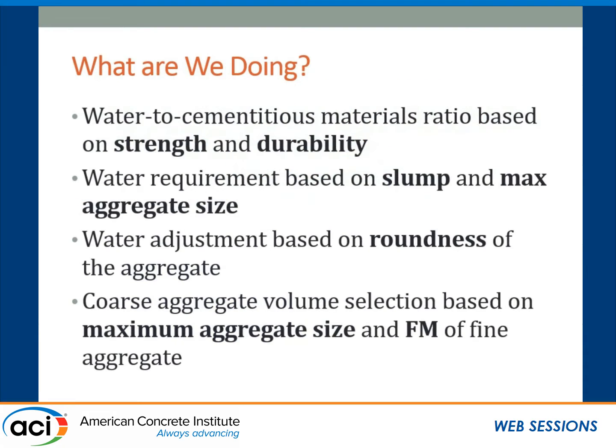I would like to briefly discuss what we are doing for typical standard aggregate mixture proportioning. Typically, we choose water-to-cementitious material ratio based on its strength and durability. Secondly, we choose water requirement based on slump and maximum aggregate size. We adjust the water based on the roundness of aggregate. And finally, we choose the coarse aggregate volume based on the maximum aggregate size and fineness modulus of fine aggregate.